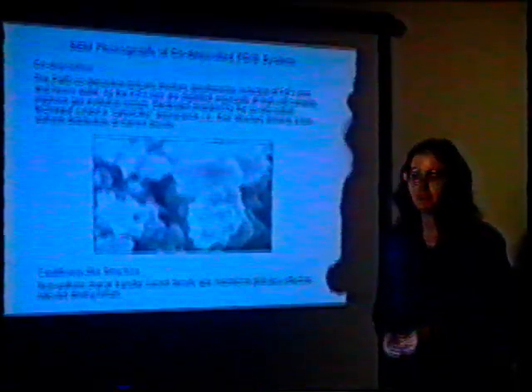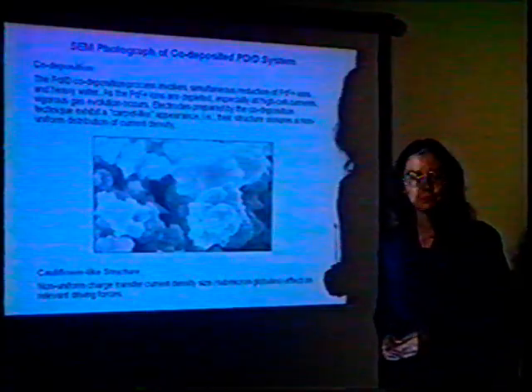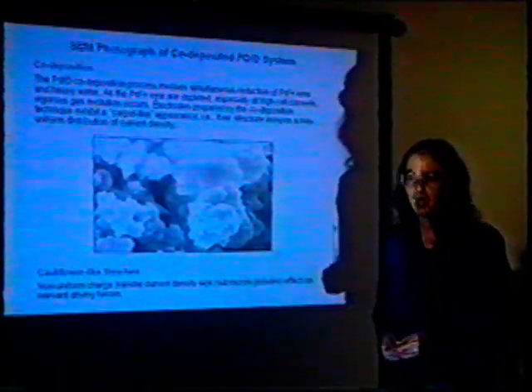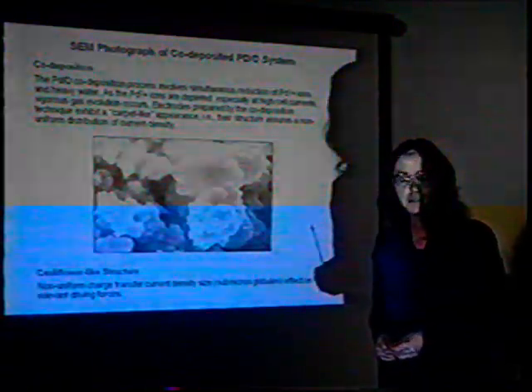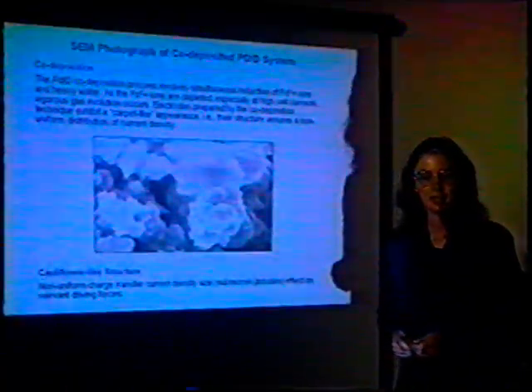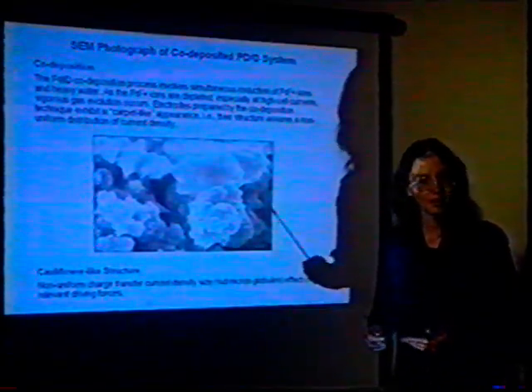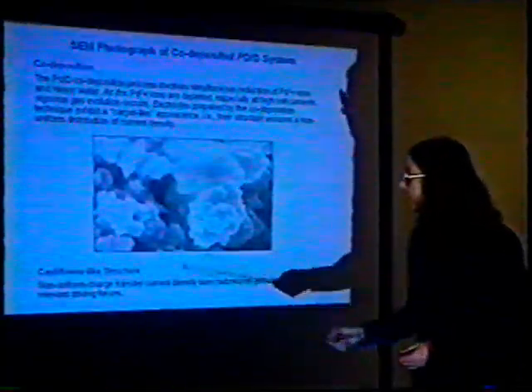Now, unlike most folks who, in conducting their experiments, use palladium rods, wires, and foils, our approach is different. What we do is palladium-deuterium co-deposition. We take our electrode, nickel mesh, copper foil. We've also used copper, gold, and silver wires. We immerse them into a solution containing a palladium salt and a background electrolyte, and we put a current there and deposit the palladium metal in the presence of evolving deuterium gas. And you end up getting this cauliflower-like structure. It's black, it's mossy, has a lot of very high surface area.